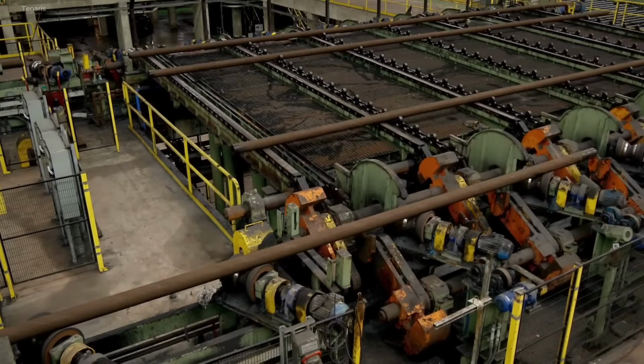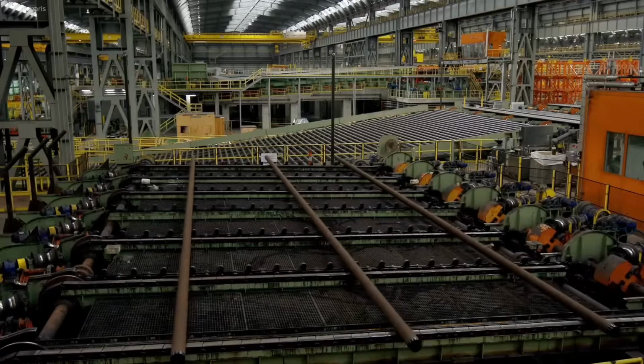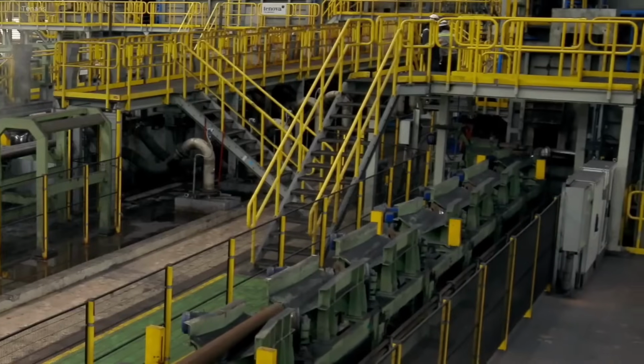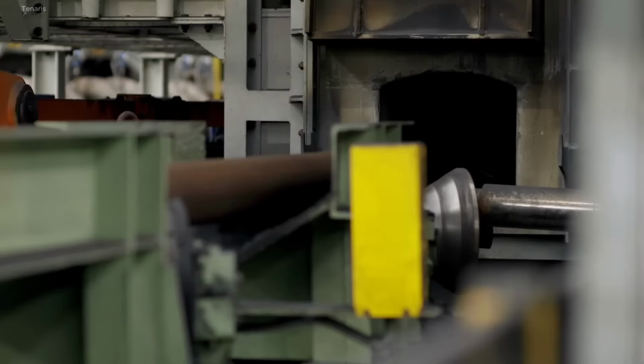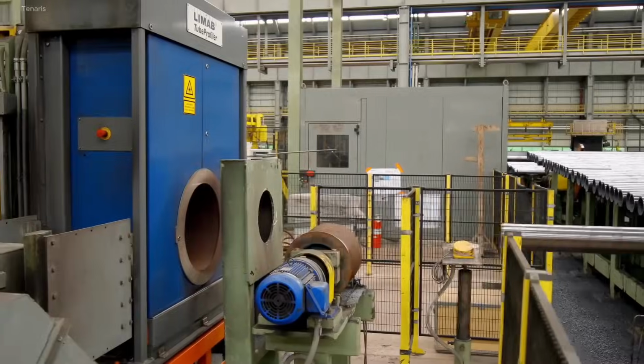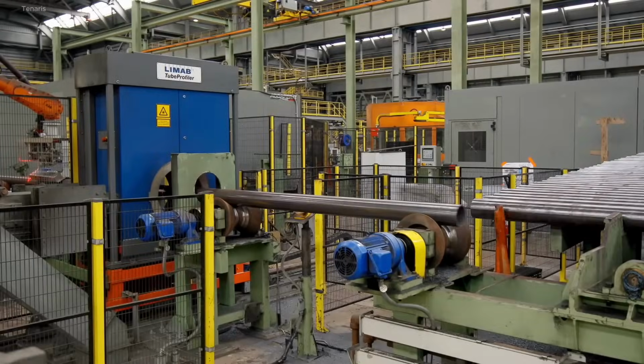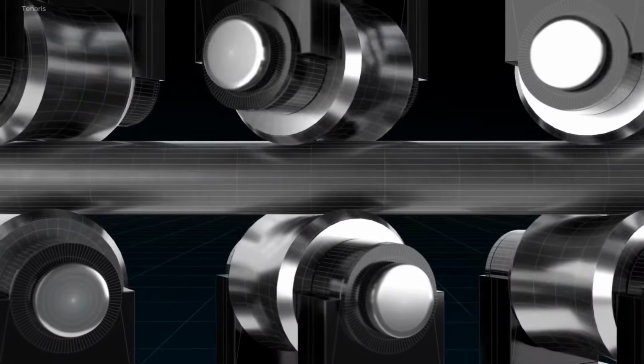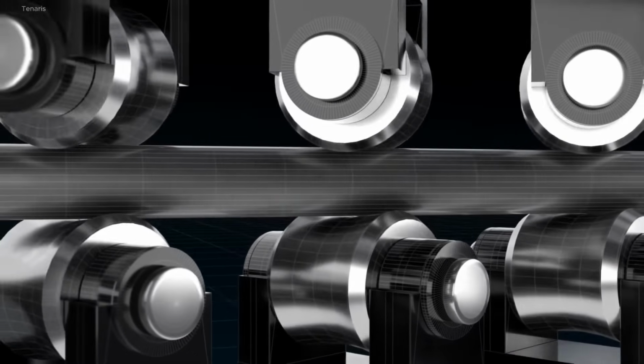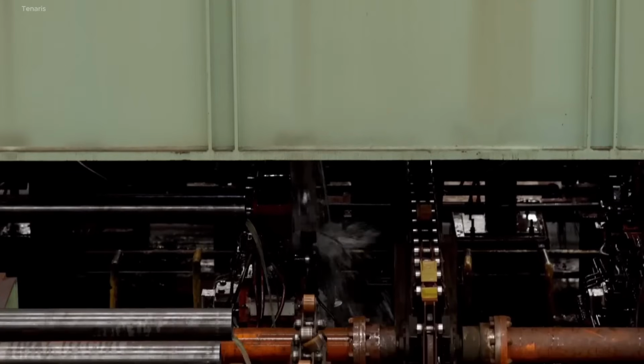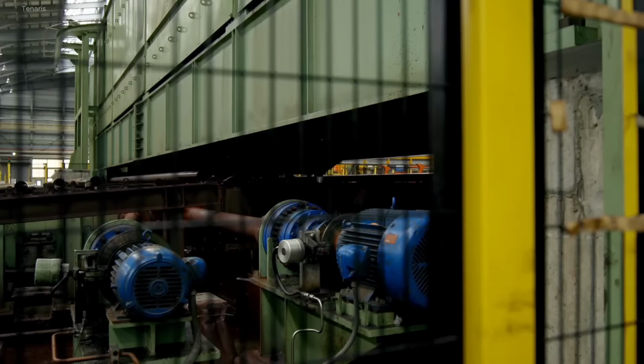Heat treatment follows, reheating above austenite transformation in the austenitizing furnace, rapid quenching to form martensite, then tempering to restore ductility. Pipes are resized, straightened, then subjected to hydrostatic, electromagnetic, and ultrasonic testing. Final processes include facing, beveling, automated threading, and coupling.